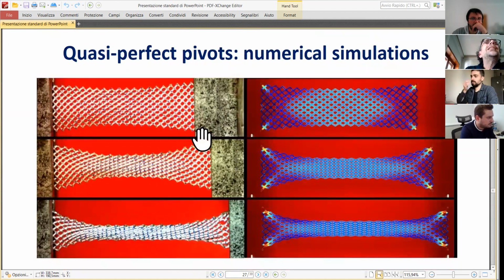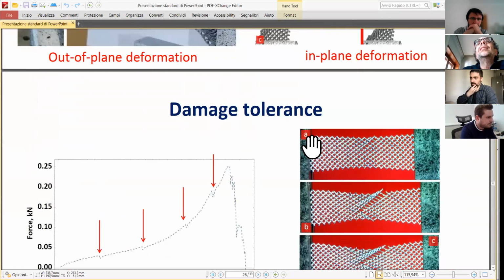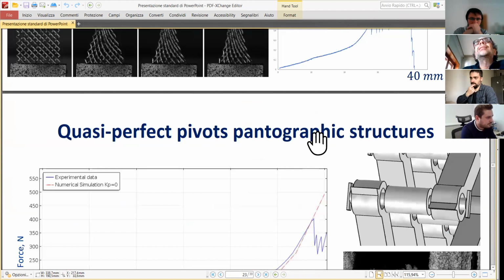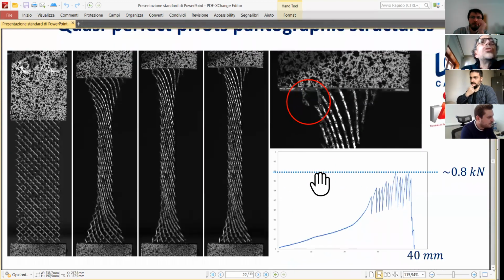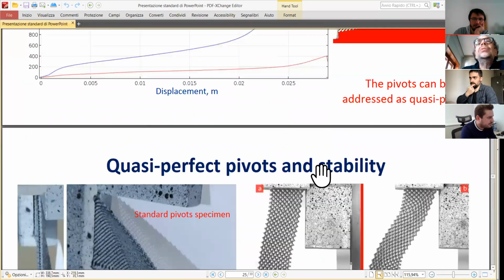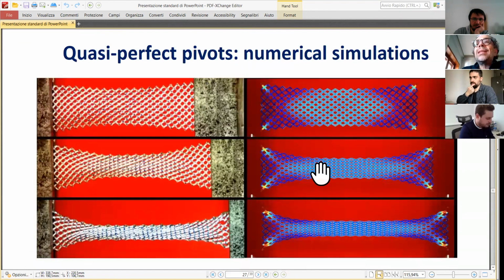Now, let me say that the energy which I gave you before is rather successful, because thanks to it, we could get these numerical simulations on the right. You see the superposition of the picture we had making the measurements, and the colors are the deformation energies. So we know exactly where are the parts of the structure which undergo the highest deformation energy. We knew that it is here that you have this concentration, and experimentally, we have seen that it is exactly here that the specimen was broken. So we have a theory which allows us to design these experiments in the best possible way.